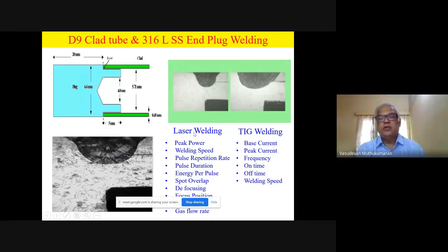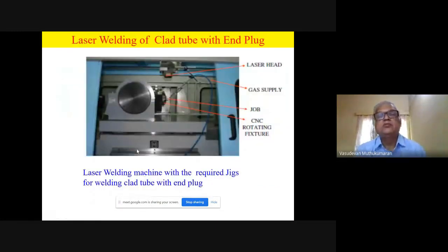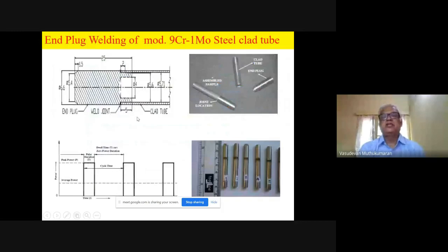These are the parameters that need to be controlled during laser welding, such as peak power, since it's a pulsed laser welding. You can see the actual welding. The tube is held here in the rotating chuck. This is the laser gun. You can see the inside views shown. Again, we could successfully weld. You can see P91 tubes can also be welded. This is a clad tube, this is the end plug, and we could successfully weld. You can see the welded clad tubes here.